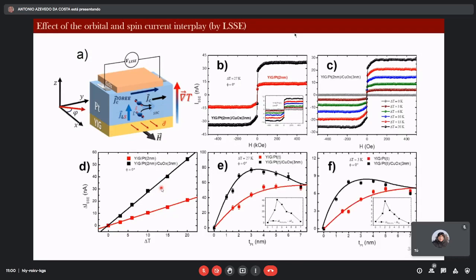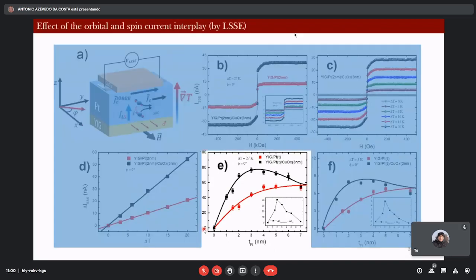We also measured the signal as a function of platinum thickness, and there is a very significant enhancement of the signal due to the presence of copper oxide. As the platinum layer thickness increases, the two signals become the same, and the signal with copper oxide becomes the same as with no copper oxide. So this is the most important result obtained by thermal spin pumping.